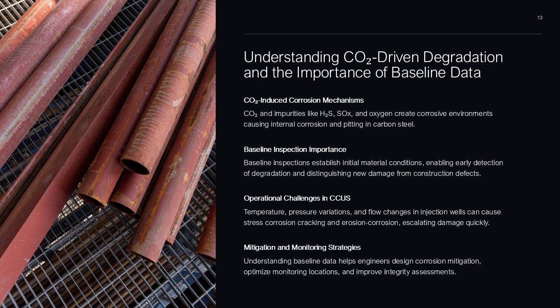Baseline inspections provide the clean starting point necessary to detect these degradation patterns early. They involve measuring initial wall thickness, documenting weld regions, verifying corrosion-resistant alloys, and capturing the original condition of coatings and linings. The baseline dataset establishes whether observed degradation during operations is new or linked to construction defects. This is particularly critical for CCUS operations because small anomalies can rapidly escalate in CO2 environments, especially in dense phase transport where flow velocities and phase transitions can amplify erosion corrosion.